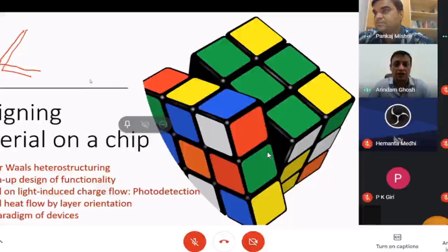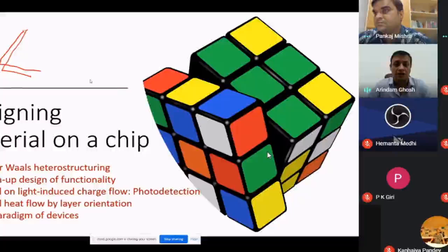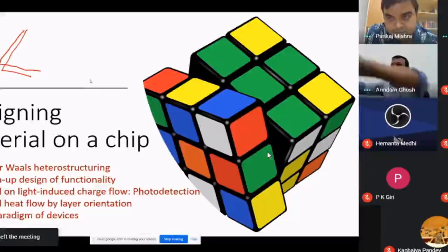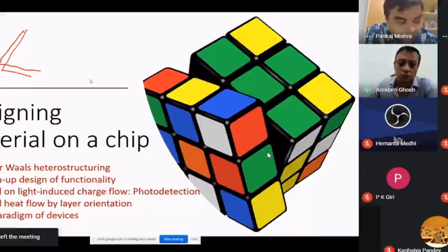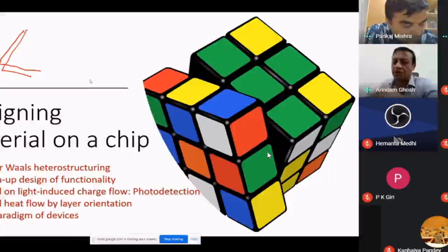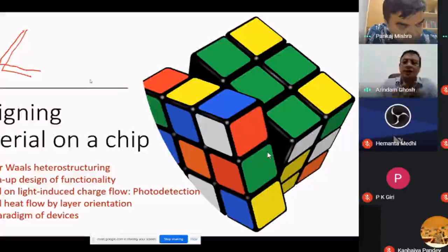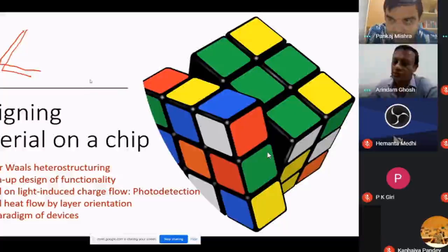Okay, let me understand the question first. I mean, you said that when we encapsulate graphene by boron nitride, because of the lattice matching, you get very large mobility. That's the way to increase the electrical mobility of these samples. Now, there has been work on encapsulating molybdenum disulfide, for example, to improve its quality. And there has been some success in that. Although, as I said in answering Saurabh's question, one of the challenges in other systems is the quality of the material, whether it is topological insulators like bismuth selenide telluride or even molybdenum disulfide. So the intrinsic crystal quality is not great, unlike graphene, and hence even by encapsulating, I don't think the increase is massive. Okay, so that's one of the problems.